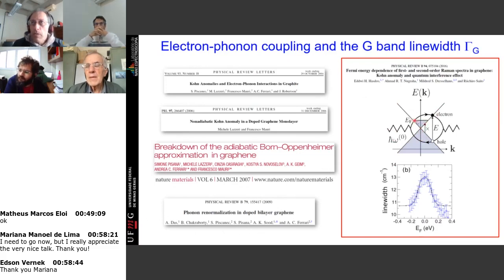So usually when it's not doped, this level here, let's call it the Fermi level, should be here. And because this is a zero gap semiconductor, the phonon can generate an electron-hole pair. So the phonon decays into an electron-hole pair. The fact that you can have this process decreases the phonon lifetime, and consequently increases the phonon line width. And once you dope the material, which means you move the Fermi level up to somewhere here, then the process cannot happen anymore because you fill it up. And then the phonon line width decreases because the process of phonon decay cannot happen anymore. So this is what was fully explained.